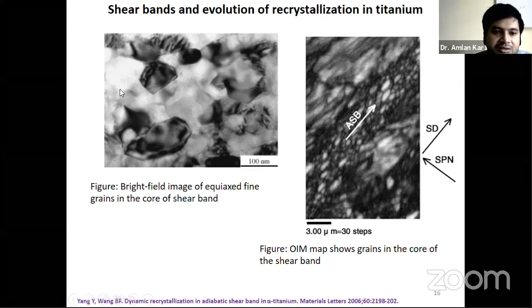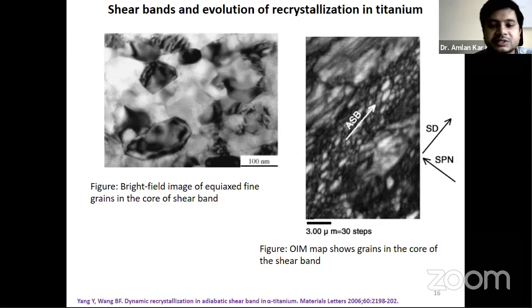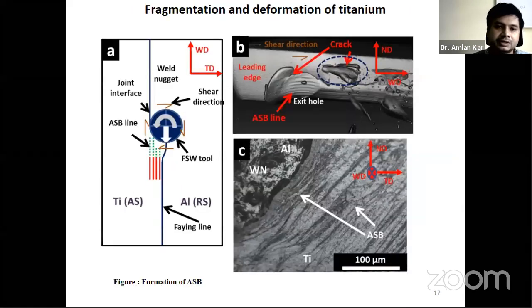And this is a bright field image of the fine grains. You can see the core of the shear bands, and there is no dislocation, there is no twinning. So this is clear evidence of adiabatic shear band driven recrystallization, which we have seen in our experiment as well.